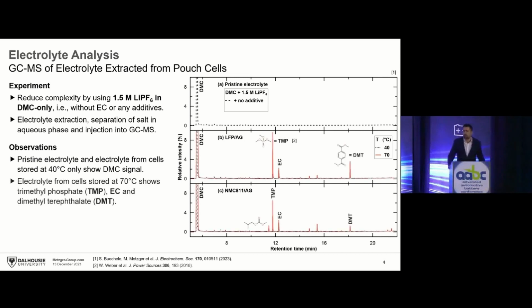So here's the data for a cell that was stored at 70 degrees Celsius, where we see this very drastic dark red discoloration and also high rates of self-discharge. And you see there are a lot of new reaction products formed, and some of them are easily explained. For example, the first major peak here, which I labeled TMP, stands for trimethyl phosphate. In fact, Martin's group published a very nice paper showing that this is a reaction product between DMC, our solvent, and the LiPF6 conducting salt.